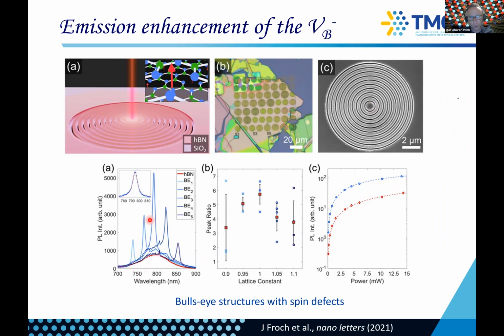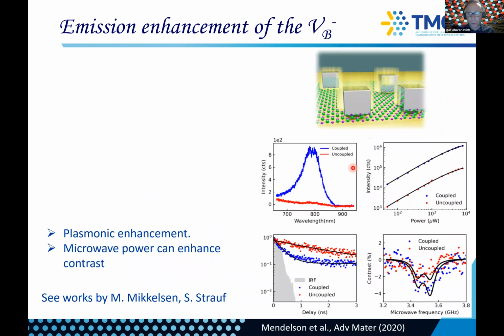And we can tune the bullseye cavity and really put a resonance right in the middle. And we can enhance your emission rate by a factor of 10 or so, but unfortunately still no singles. So the other way to go is really going plasmonic gap cavities. And so here, this was inspired by work of Michael Mikkelsen and Stefan Strauff.